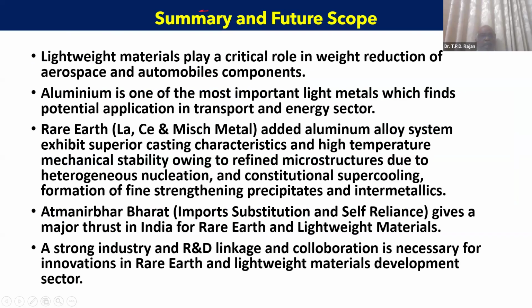So to summarize my talk, lightweight materials play a critical role in the weight reduction of aerospace and automotive components, and aluminum is very widely used. Aluminum alloys among the transport and energy sectors, and here the importance of rare earth addition into the aluminum alloys, either in the form of lanthanum, cerium, misch metal, or the scandium, is mainly it improves the room and high temperature properties of these composites or the alloys, owing to the refined microstructure, due to heterogeneous nucleation, constitutional supercooling, or the formation of very fine precipitates of aluminum scandium precipitates, or the aluminum cerium precipitates, or aluminum lanthanum precipitates, which overall strengthens the alloys.